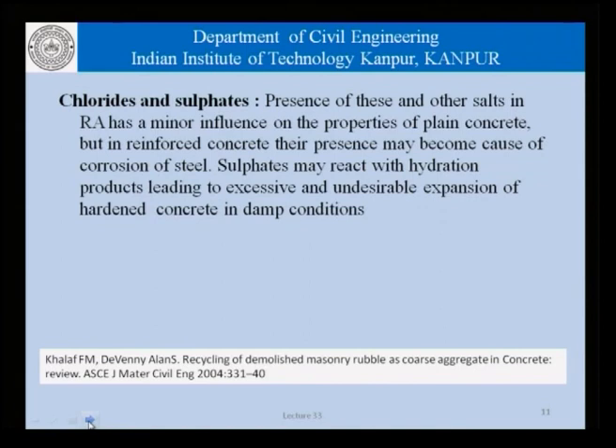Continuing our discussion on contaminants in recycled aggregates, there are chlorides and sulfates and possibly other chemicals. Presence of these and other salts in recycled aggregate has a minor effect on the properties of plain concrete, but in reinforced concrete, their presence may become the cause for corrosion in steel. Sulfates may react with the hydration products, leading to excessive and undesirable expansion of hardened concrete, especially in damp conditions.